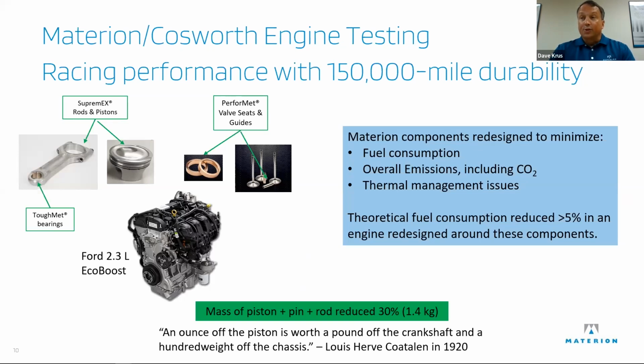So the SupremEX is, I'll tell you more about it in a minute. It's a metal matrix composite aluminum that was used for the rods and the pistons. We had our ToughMet alloy in the small end bearing. And PerforMet, which many of the people on the call will recognize, was used for the valve seats and the valve guides. And the whole idea was to, can we reduce the fuel consumption? How much can we reduce the fuel consumption, which will reduce the emissions? Can we manage the heat better with the PerforMet, with the higher conductivity materials?